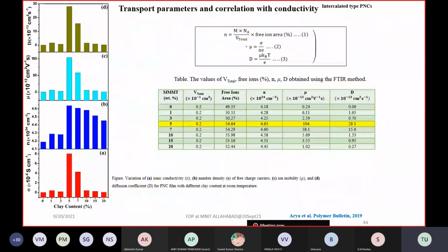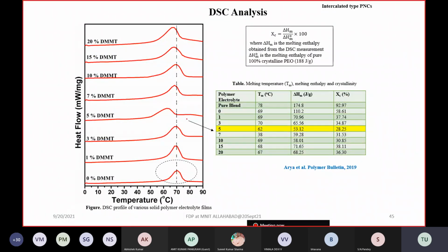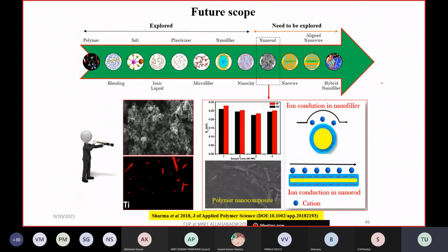At the same time, we have calculated these transport numbers. Actually, transport numbers, if I may say, depend on the number density, the viscosity, and the diffusion coefficient. All these three factors, with respect to clay concentration, we have calculated, and for the same concentration, you see its value is high. So this is the way it is to be analyzed, and DSC is also going to be analyzed in order to find out that at the same concentration where intercalations occur, it mostly shows amorphous behavior. For amorphous behavior, it gives the better ionic conductivity value. So it is actually helpful.